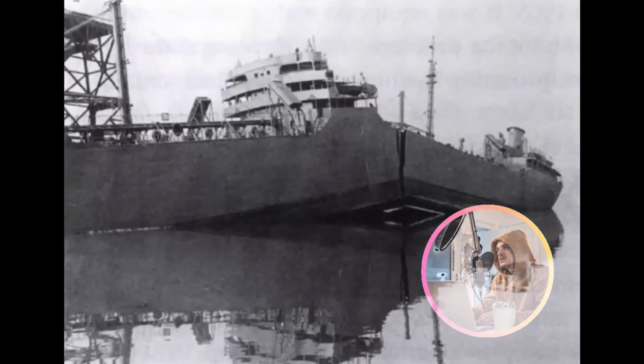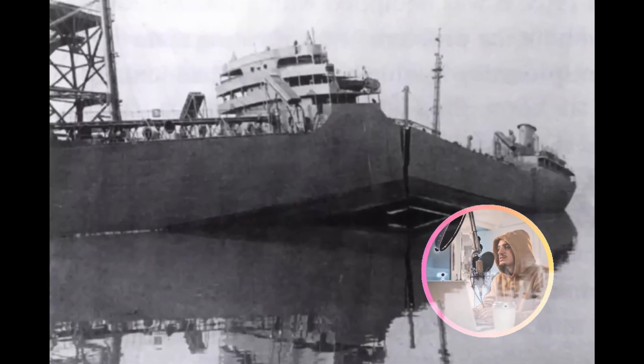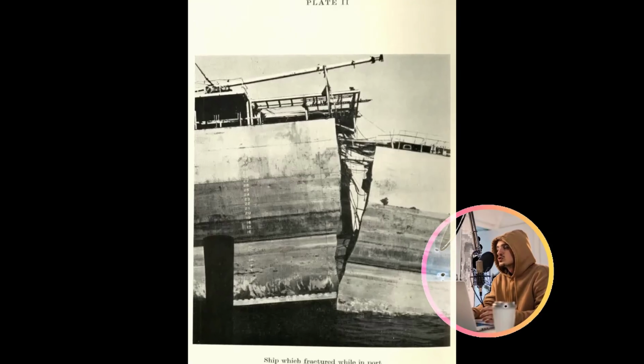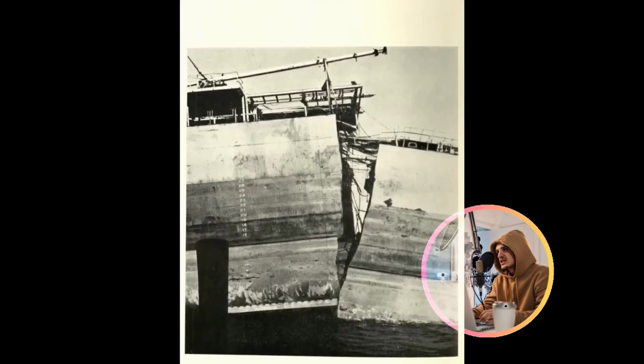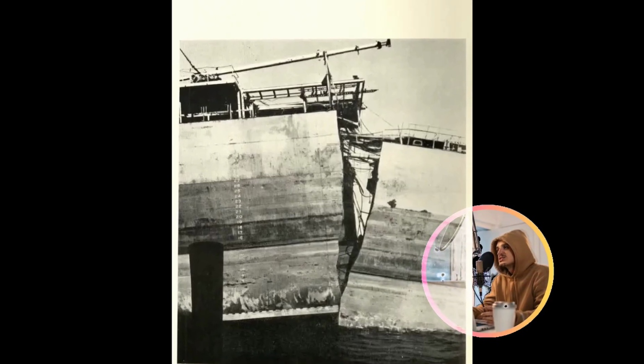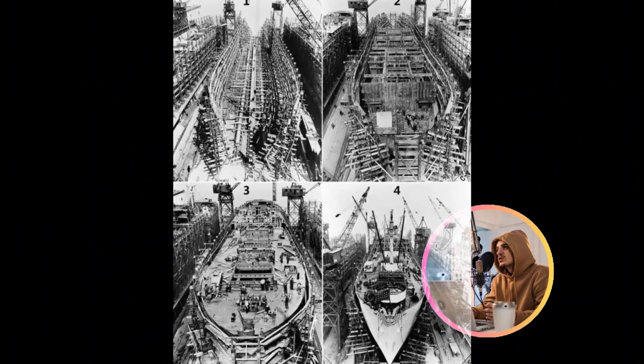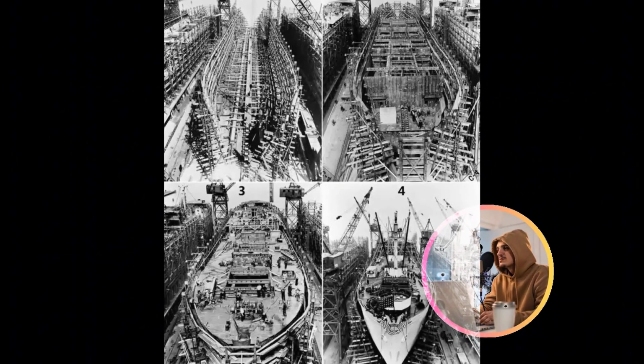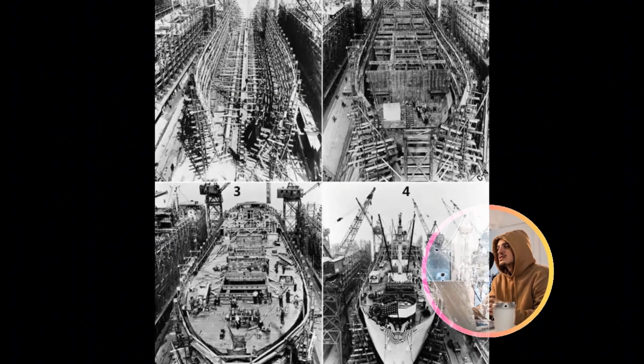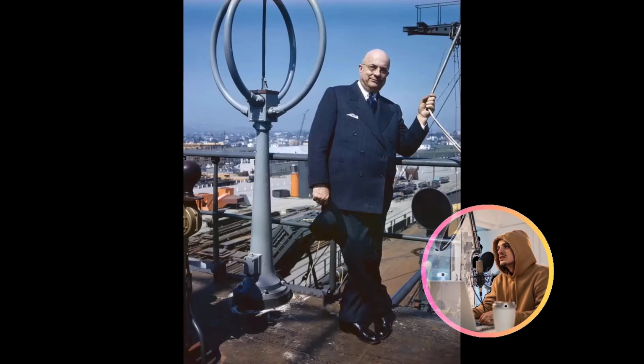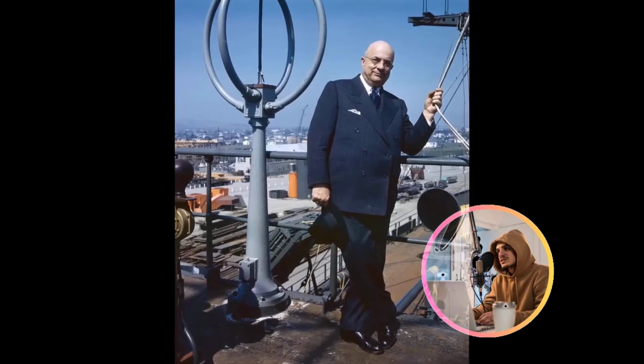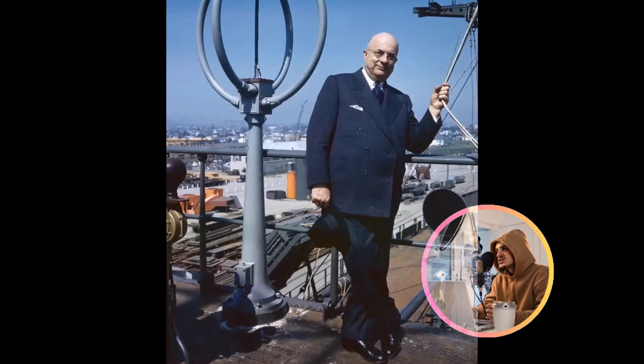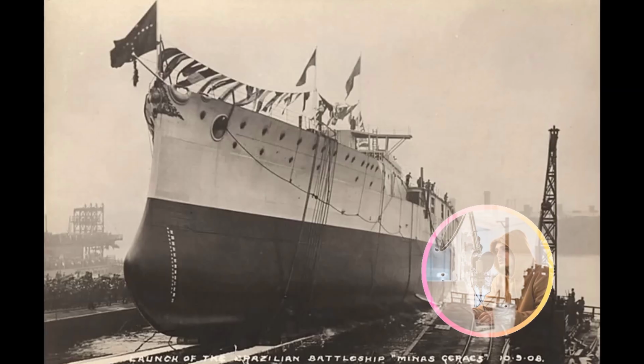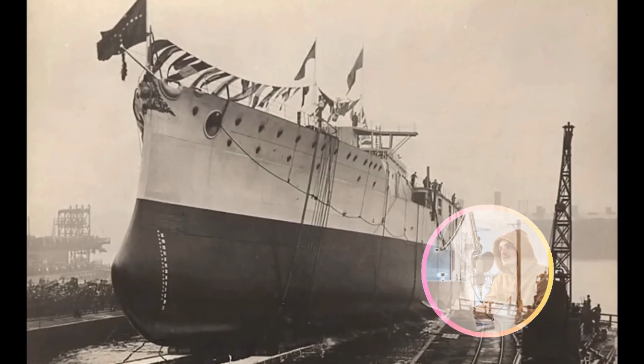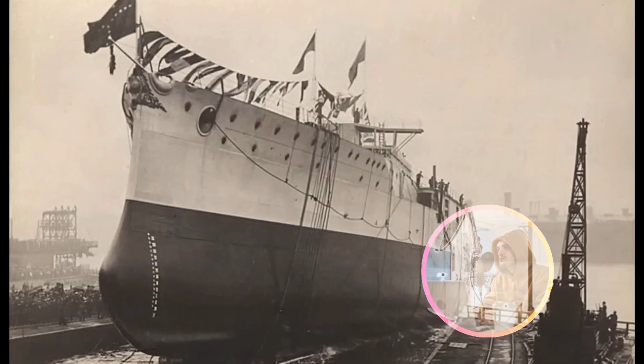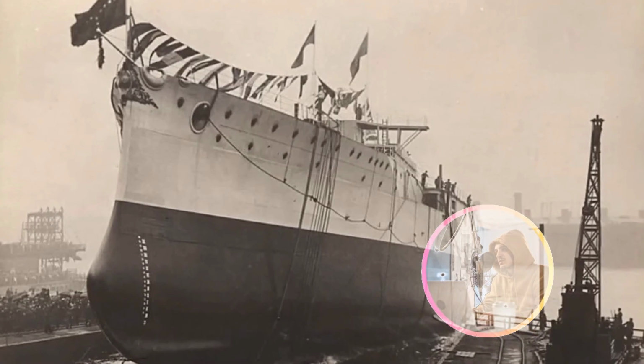The latent potential energy embedded within these persistent internal stresses provides the irresistible impetus for the crack's relentless expansion. Acute angles function as potent focal points for stress, amplifying the localized strain by magnitudes of 3 or even greater. The fissure then gains incredible momentum, occasionally surpassing the velocity of sound waves propagating through steel, tearing through the ship's structural integrity before any internal partitions or reinforcing ribs can effectively impede its catastrophic advance.